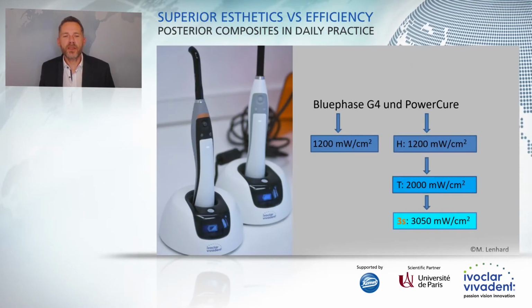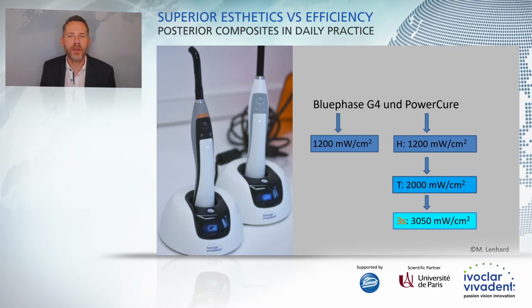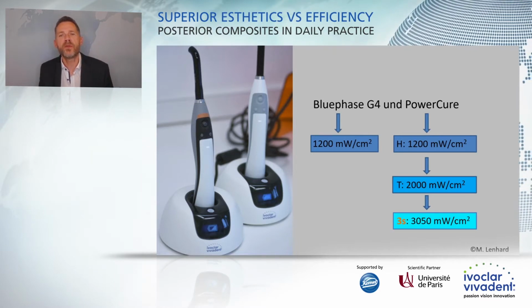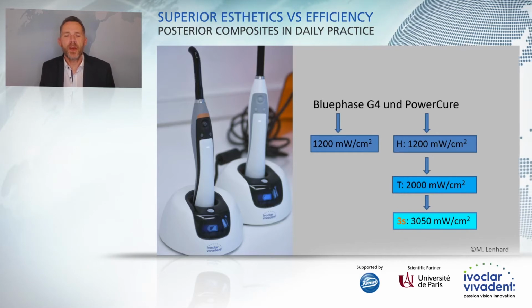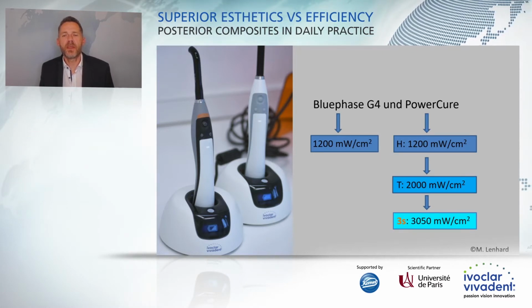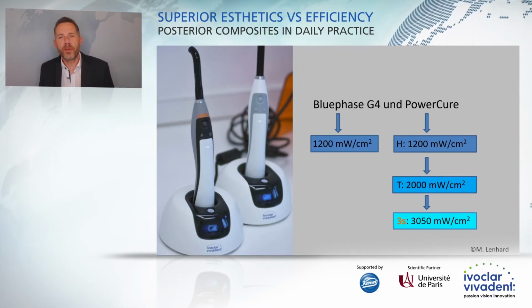Now, when you look at the latest generation of curing lights from Ivoclar and Vivadent, they have what they call a curing assistance. I would say it is an educational tool to guarantee that you do the light curing correctly. The two curing lights that you see here is the G4 with a power output of 1200 milliwatts per square centimeter, and here the Power Cure with a power output up to 3000 milliwatts per square centimeter, where you can actually light cure the latest generation of bulk fills, the Tetric PowerFill, in as little as 3 seconds per layer.